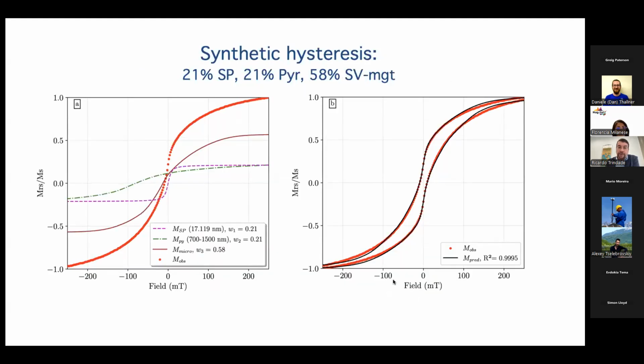Based on all the measurements we have done and all the modeling, we were also able to model the hysteresis, the inversion of all grains that we modeled from that small pillar. When compared to the bulk measurement of hysteresis, it provides a mixing between several different contents that were observed from the images and also from the micromagnetic modeling.